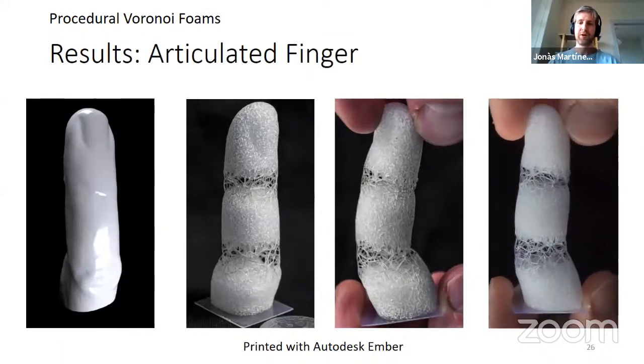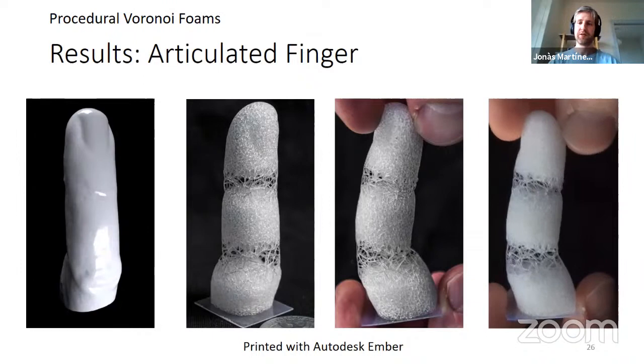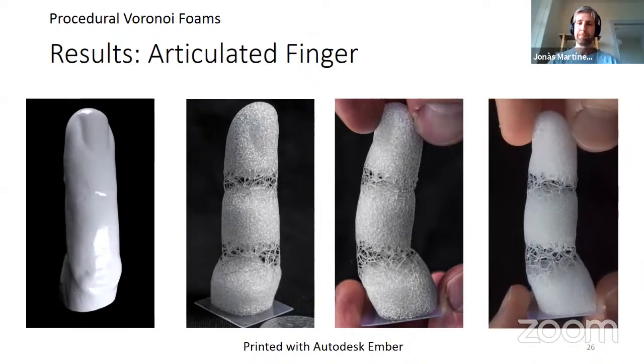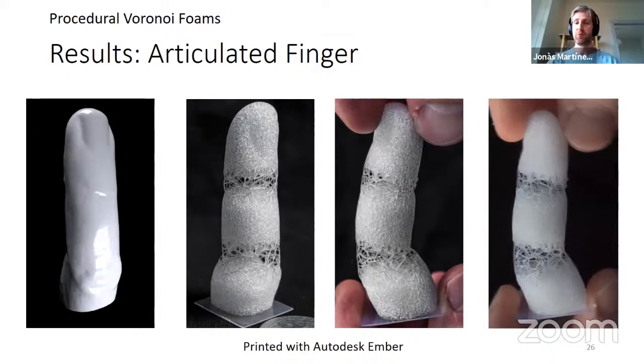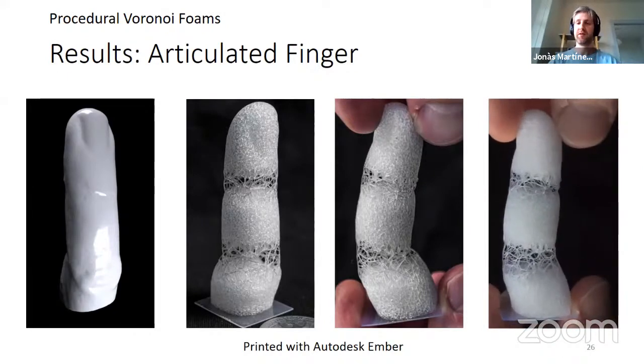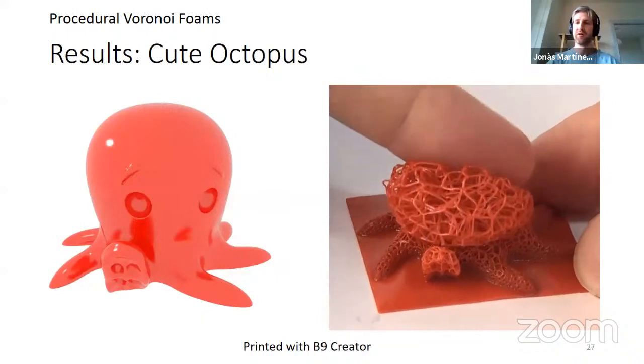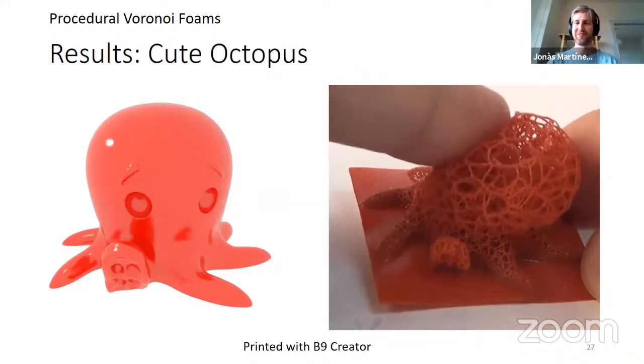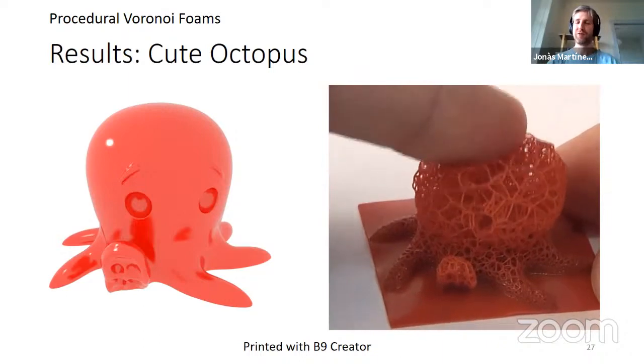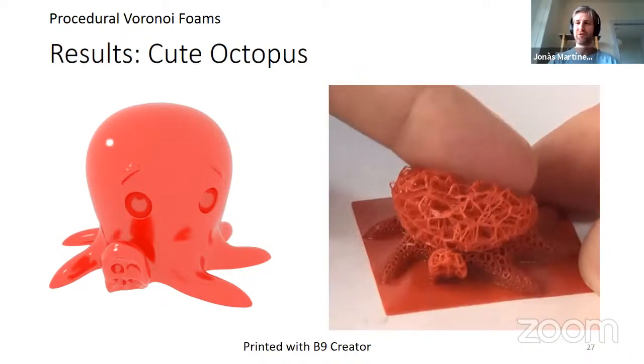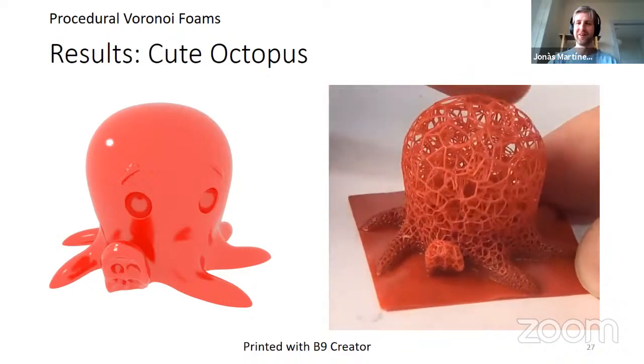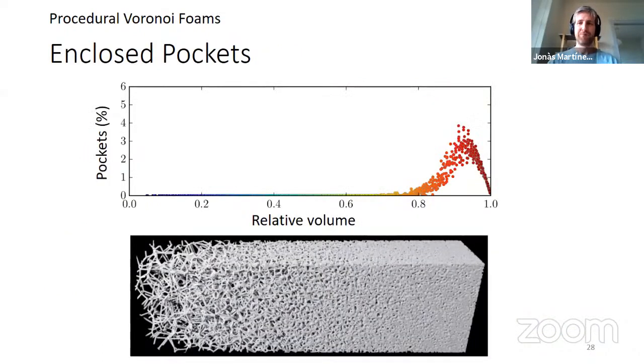Here is another finger, articulated. So basically here we're playing with different Young moduli to obtain the movement on the articulations. And here, this fluffy and cute octopus is still surviving in our office after all the compressions we did. As you may have wondered, of course, if your relative volume goes close to 1, at some point you will start having pockets, but that's something that you cannot escape.